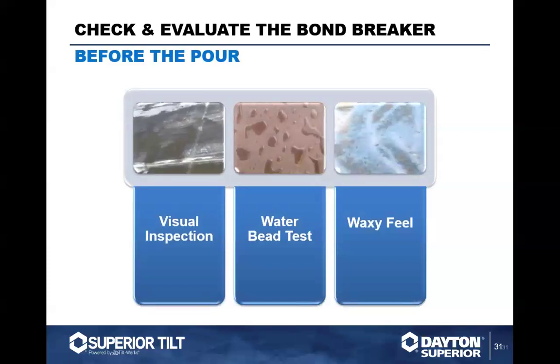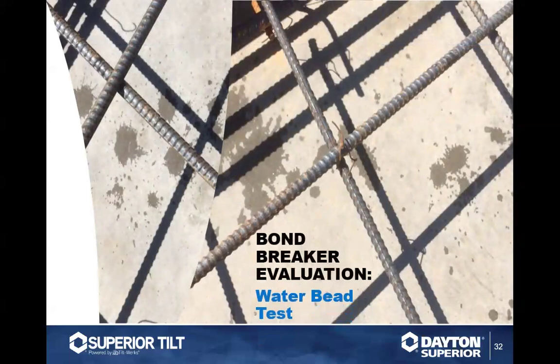I remember the first time I ran out onto a job site, and the engineer was walking around with me, and I've got a bottle of water in my hand, and I'm sprinkling water on the slab. Well, what I was looking for is that middle section here that says water bead test. If the water beads up on the concrete, you have enough bond breaker in place. But if it doesn't bead up and you get something like this where it looks like it's soaked right in, you don't have enough bond breaker in.